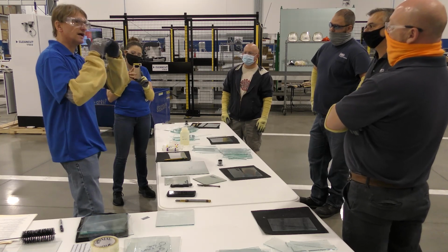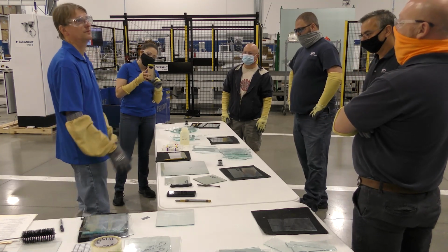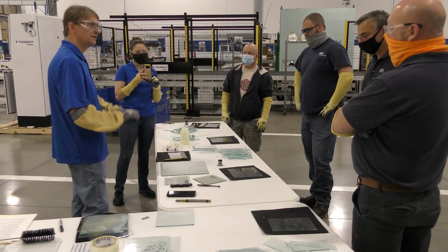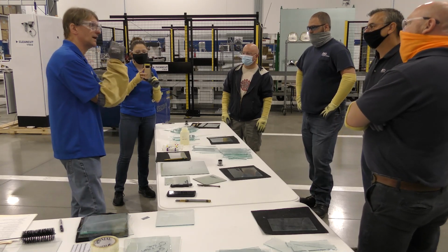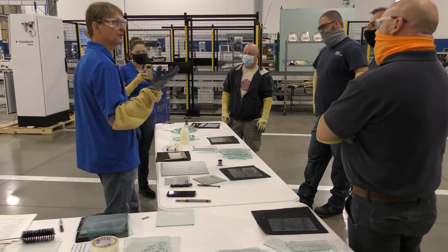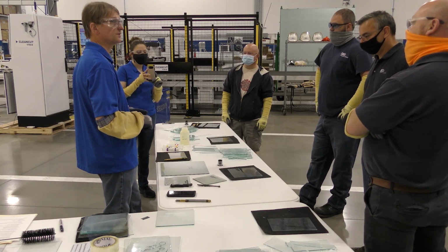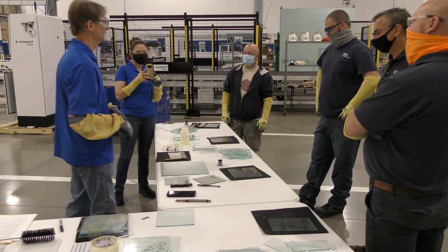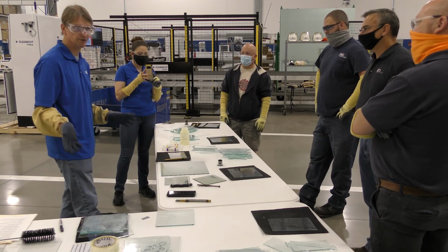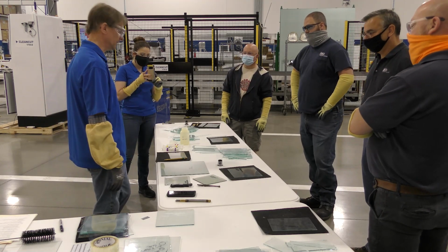And then it goes up from there. So the thicker glass, you need 15, 20 pounds of force, maybe a little bit more for the really thick stuff. And then you get into the really thick stuff, and you might need brake assist. So clamp or pliers, like tile cutters, where they've got the tile breakers, where you need to put that edge into stress. But on the 3/4 and plate glass, you sometimes need clamps and tools to break that. But for what we're doing with residential and IG, typically that's not the case.